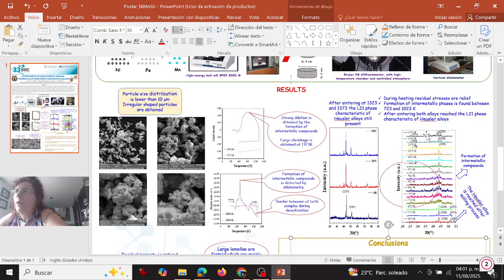And in here we can see that during heating residual stresses are relieved, and we can also see that the formation of intermetallic phases was found between 723 to 1023 degrees Kelvin. Another observation was that after sintering, both alloys reached the L21 phase, characteristic of the Heusler alloy. So the formation of intermetallic compounds we can have it here, and also the Heusler alloy is reached after the milling process. All right.